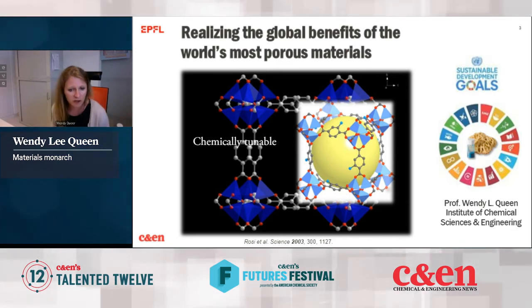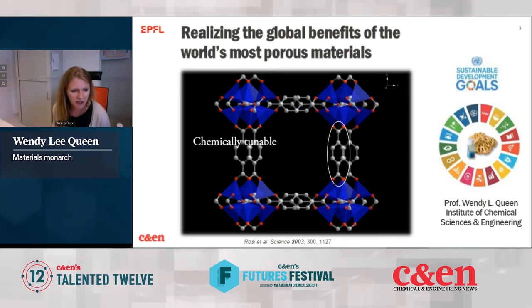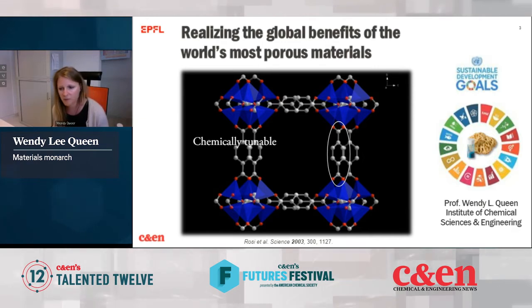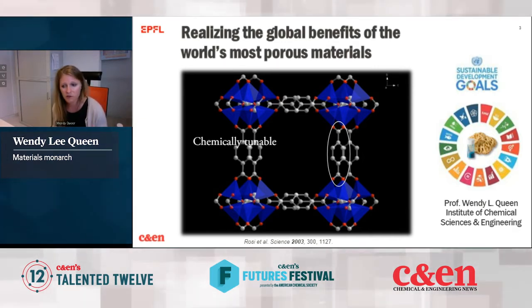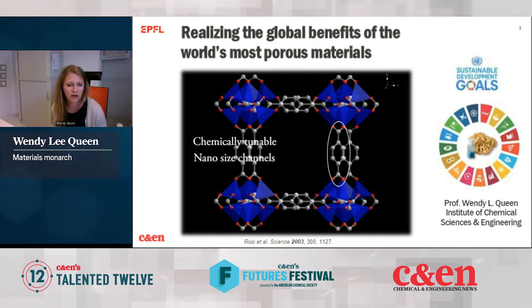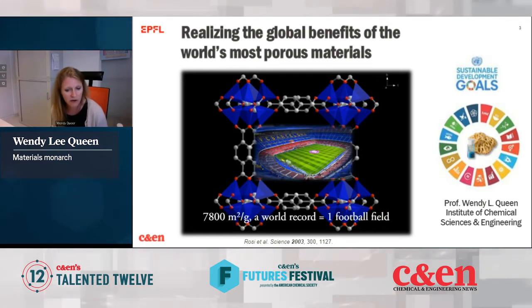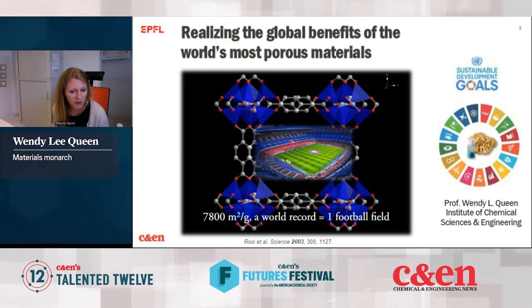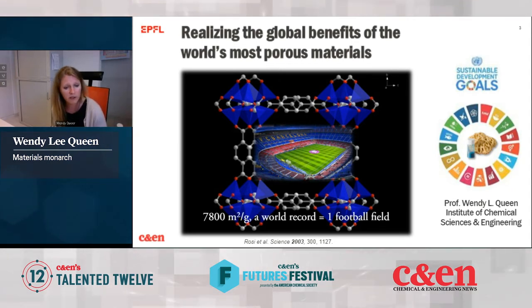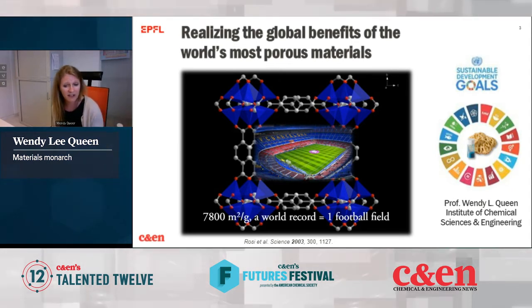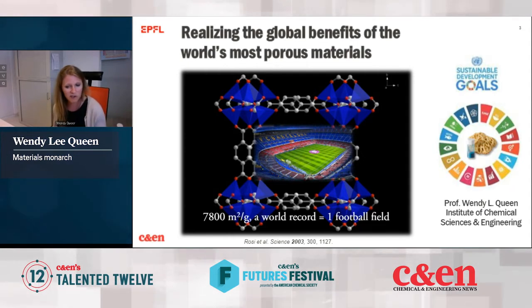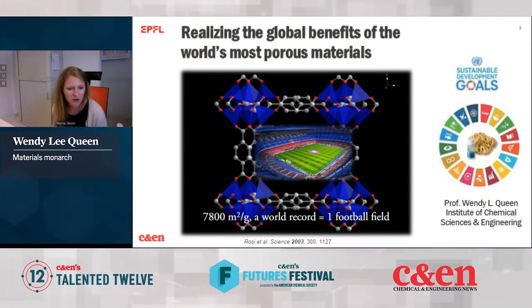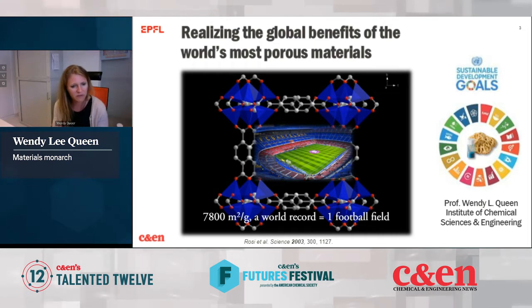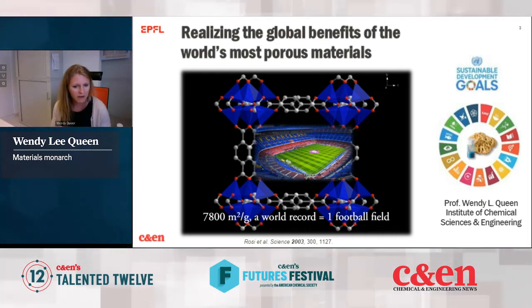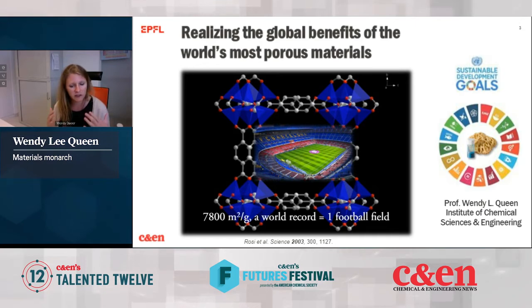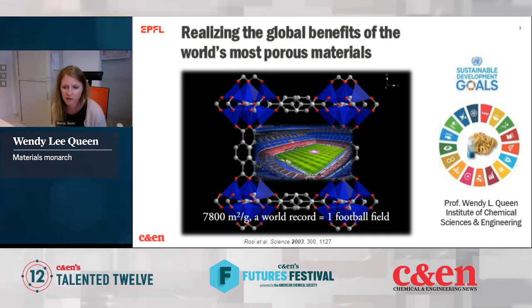So if you take a closer look at this material, you'll note that it has very high densities of very small pores, so it's mostly open space. And as a result of this high density of nano-sized channels, they actually have record-breaking surface areas. So the record at the moment is about 7,800 meters squared in a single gram. And just to give you an idea of how much surface area this is, it's equivalent to that of a European football field. So not only can we chemically tune them to selectively grab certain guests, we also have very large surface areas, and this means that we can put a lot of things inside.